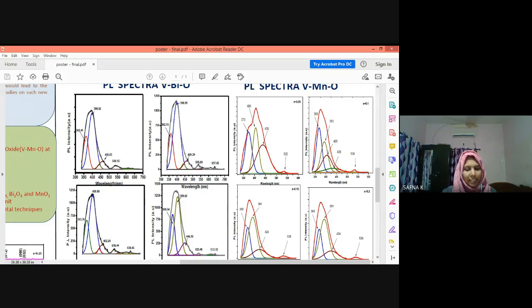The emission at 370 nanometers is due to valence uncertainties of vanadium, and the one at 400 nanometers indicates excess presence of V4+ ions along with V5+ ions in the crystal. And the 460 nanometer emission has an energy higher than the bandgap energy and might be due to recombination of electrons from high levels of the valence band and conduction band. And the low intensity indicates oxygen deficiency related defects in the crystal.